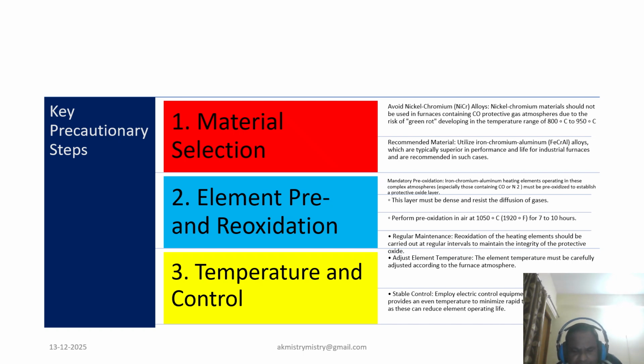A key precautionary step is avoiding certain alloys in specific environments. Nickel chromium material should not be used in a furnace containing carbon monoxide protective gas atmosphere. The reason is the risk of green rot developing in the temperature range of 800 to 950. In contrast, ferrochrome aluminum alloys are superior and recommended for industrial furnaces used in such complex reducing environments.